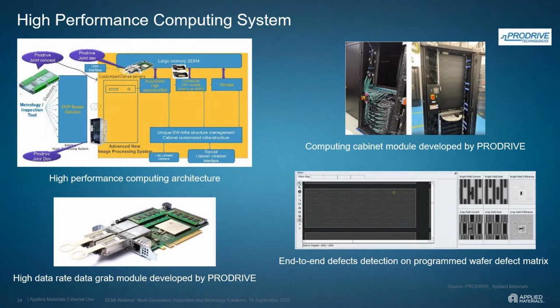On the right, we can see the computing cabinet module, which is a complex module of its own developed by ProDrive. Bottom left is the high data rate grab module, which was developed by ProDrive. The top left is a scheme of the computing system, which is scalable for the bright field inspection. And in the bottom right, we can see end-to-end defect detection on programmed wafer defects matrix, showing that this high-performance computing system was integrated successfully and is yielding the required detection.